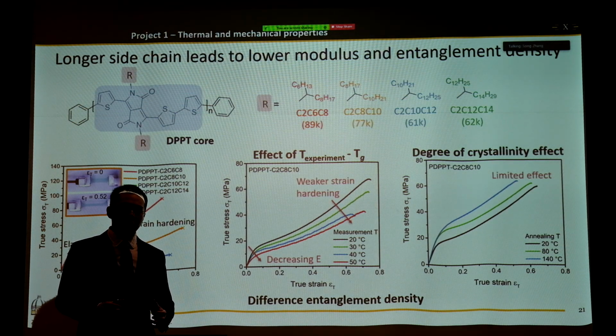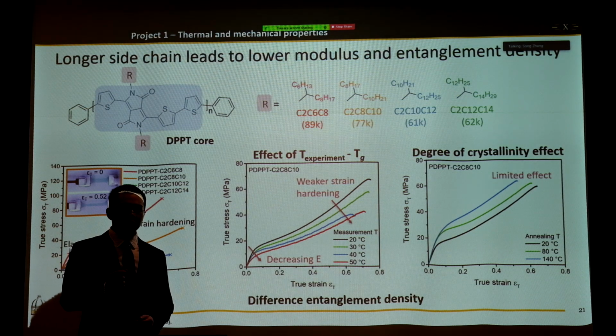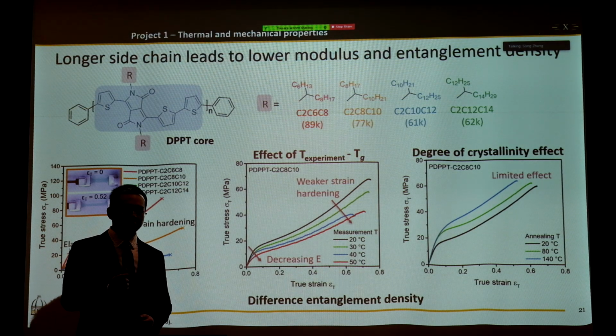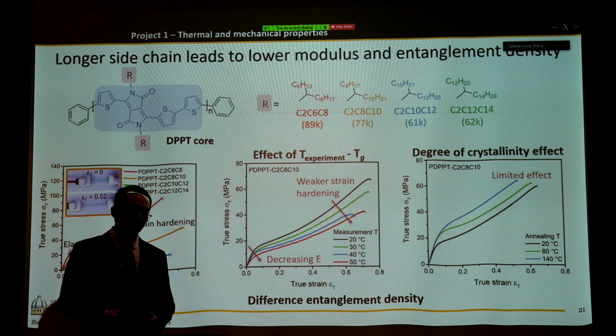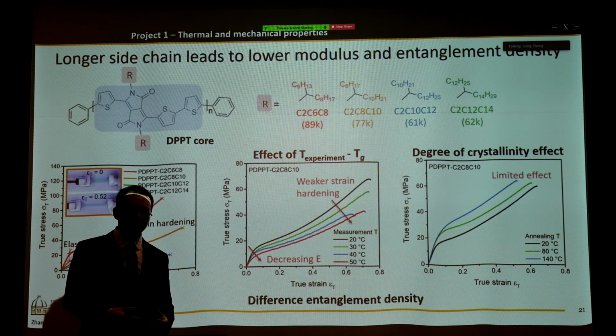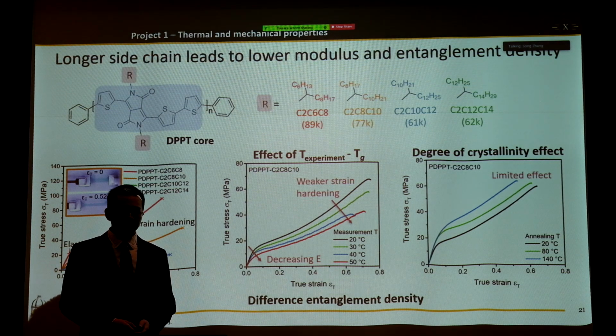And now we only have one other option, which is the degree of entanglement density. This property will be measured through rheological measurement, and such an experiment is underway. And we think the temperature and entanglement density both contribute to the different strain hardening behavior.